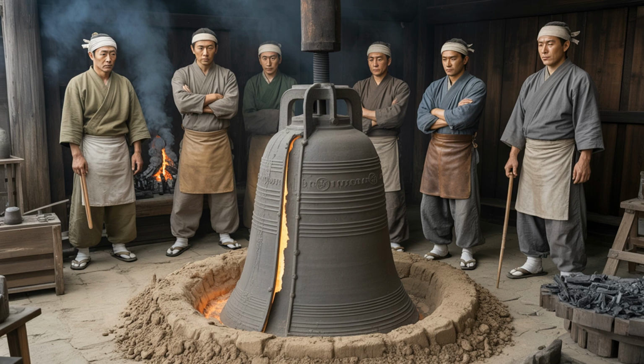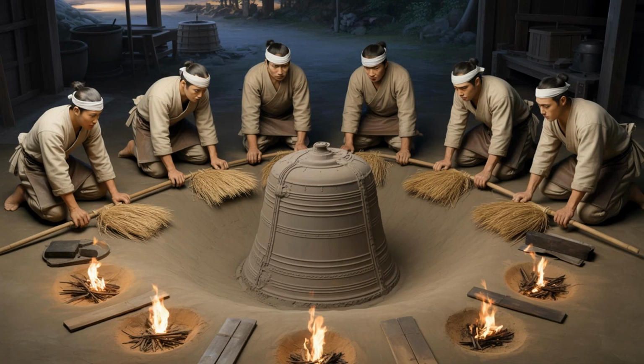The buried mold, now full of liquid bronze at over 1,000 degrees Celsius, had to cool slowly and evenly to avoid cracks. The cooling process was perhaps the most nerve-wracking part of the entire operation. There was nothing to do but wait and hope. The mold was buried in sand or earth to insulate it and promote even cooling, but internal stresses were building as different parts of the bell cooled at different rates. The thick sections would stay hot longer than the thin sections, creating thermal stress that could crack the bronze if the cooling wasn't controlled perfectly.